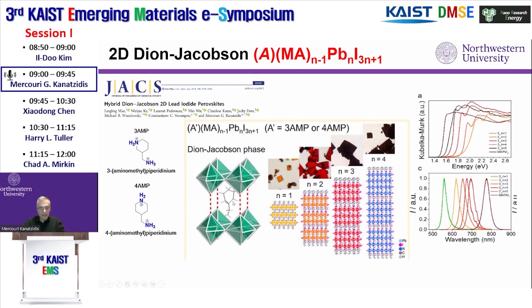It's not exactly the same as the other, the Ruddlesden-Popper. Here, to get Dion-Jacobson, you need a short spacer, like these spacers here, relatively short, and you need dications. And when that happens, in between the layers, you get this case. And that forces the iodine here and the iodine here across the layers to talk to each other. They touch each other, and they in fact interact positively to change the properties of the perovskite. That's why for the same thickness, these perovskites have lower band gaps than the Ruddlesden-Popper band gaps.